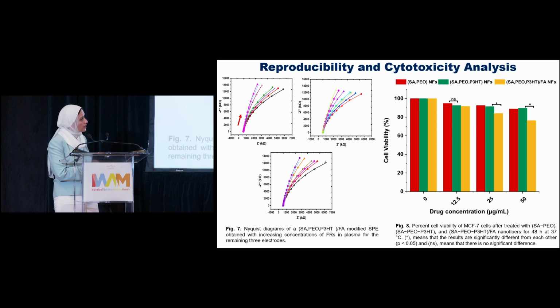And finally, we examined the biocompatibility of our biosensor by incubation with MCF7 breast cancer cell lines, for the 3 layers: the biopolymer nanofibers, after conjugation with P3HT, and after adding folic acid. We obtained no significant cytotoxic effect against cell lines. The viability was around 90%, except for the 3rd layer after adding folic acid, where maybe there is a little significant difference.